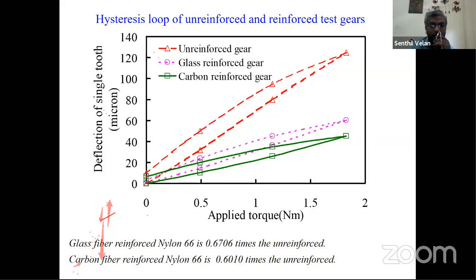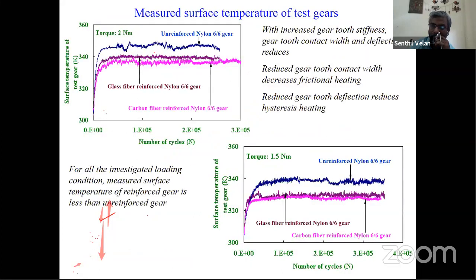So if you look into this, these are the measured surface temperature. This is the deflection. This is the measured surface temperature. Again, we made use of some non-contact techniques with an IR camera. We measured the surface temperature of the gear. It is not the exact temperature, but the relative temperature. So the relative temperature, if you see that, naturally the unreinforced one is showing higher temperature, because the dissipation, the heat generation is also more, as we just saw that the hysteresis loop is larger in size. When you add the fiber, naturally this loop size is smaller and smaller. You will be able to see that in that way, the internal heat generation will not be more when you add the fiber.